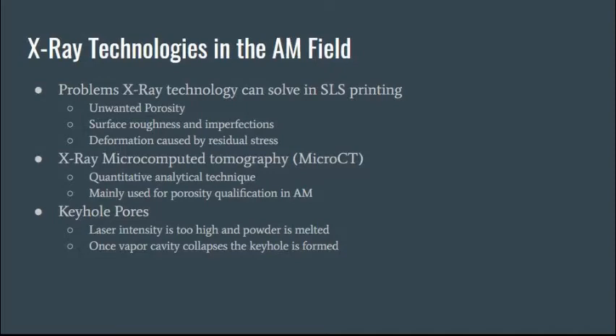Deformation caused by residual stress is, as the printer is moving layer by layer, it heats where it is fusing the material to the solid object, and that heating and cooling at every layer causes residual stress to occur. And this deforms the final part so that it no longer matches the dimensions that were modeled on the computer. And to solve this problem, engineers and scientists have turned to XCT, or X-ray microcomputed tomography. This is a quantitative analytical technique, and it's mainly used for porosity qualification in additive manufacturing.